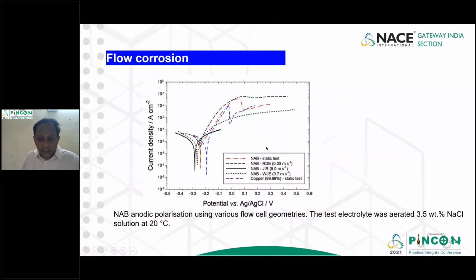Then this was a flow corrosion. I did a corrosion and a flow corrosion in my wall jet electrode. What I was trying to tell you is, if you look at the static case, the blue color one, this is formation of a cuprous oxide and transformation to a cupric oxide. But in the jet impingement case, I was not able to see the formation, because the cuprous chloro complex was not able to precipitate on the substrate and was carried away by the flow. So that's why it was not able to give any corrosion resistive properties. This oxide film was not able to form. The same thing I could see here: the jet impingement is complete dissolution, so the cuprous chloride complex was not forming.